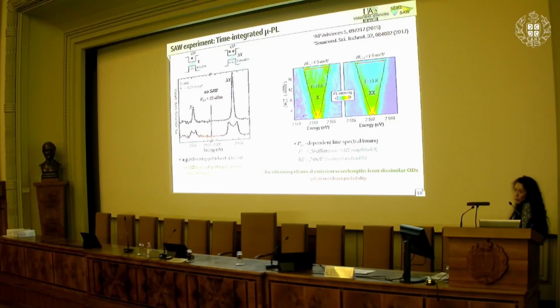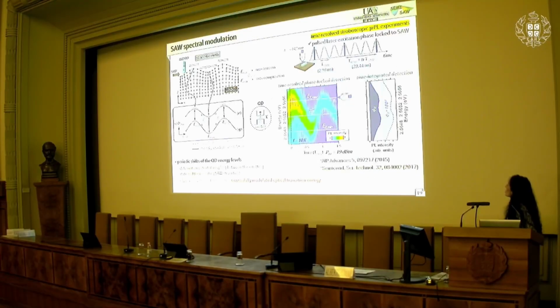Now, this is actually an important result because with this, we can tune the emission energy of similar quantum dots and force them to emit at the same wavelength, which is quite important for quantum communication and computation technologies. The spectral changes that we observed on the previous transparency are basically due to periodic shifts of the quantum dot energy levels that I illustrated here, induced by deformation potential coupling between the emitted states and the oscillating, acoustically induced mechanical vibration.